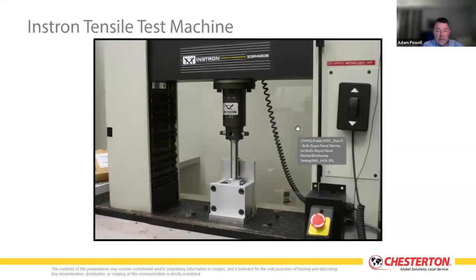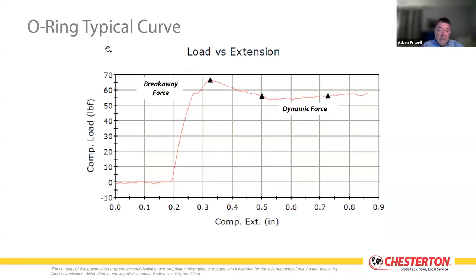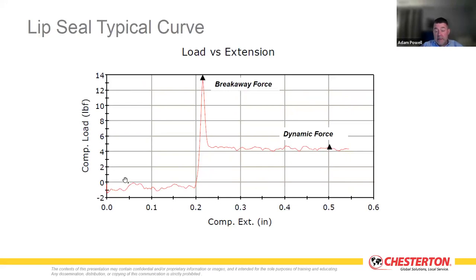This was the fixture. Now this is the load extension curve we had for a typical O-ring. So the load was just being applied, no movement, load increasing, and we begin to get movement. And then as we got into the dynamic range, the load stayed fairly similar to the breakaway load. So this is the breakaway point, and then this was constant motion. And then this is a U-cup seal. So loading up, the breakaway point. After breakaway, the constant motion, the loading is significantly lower.